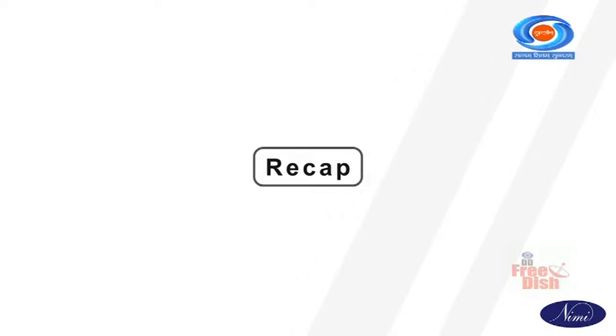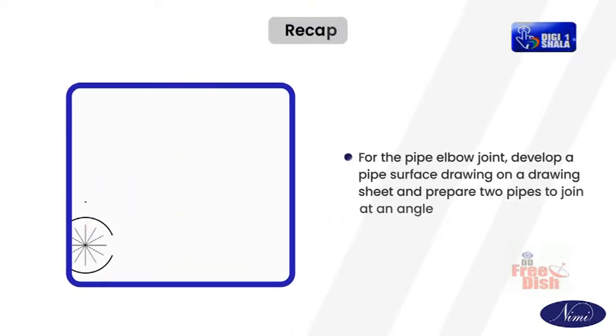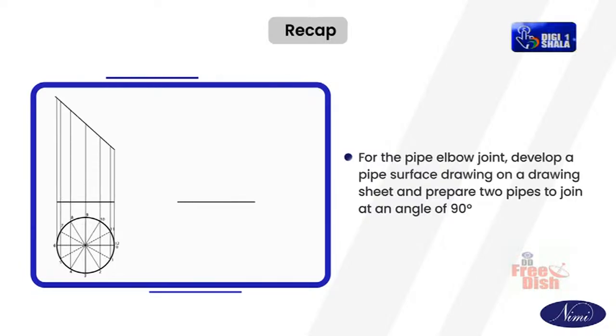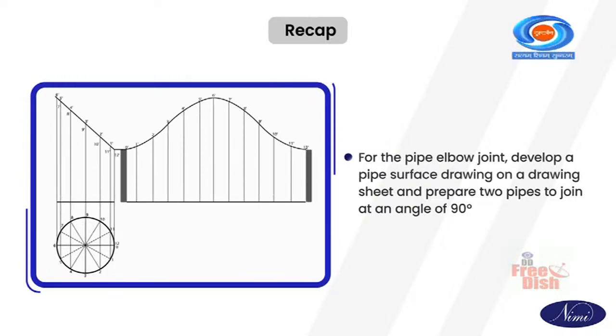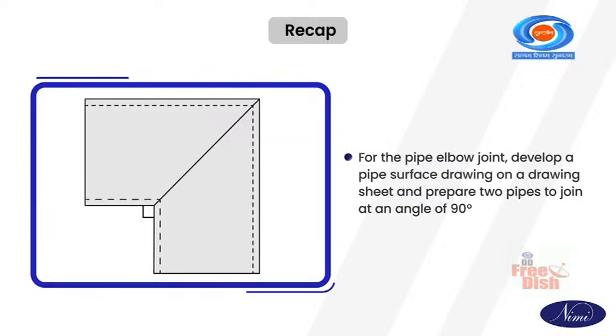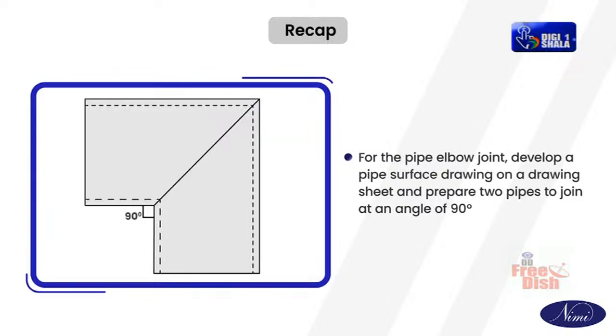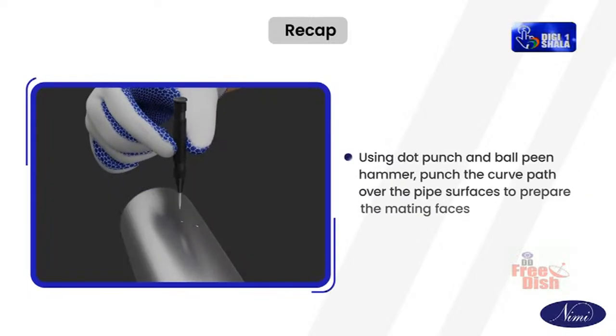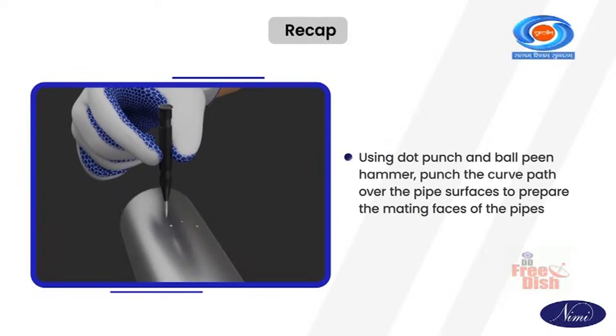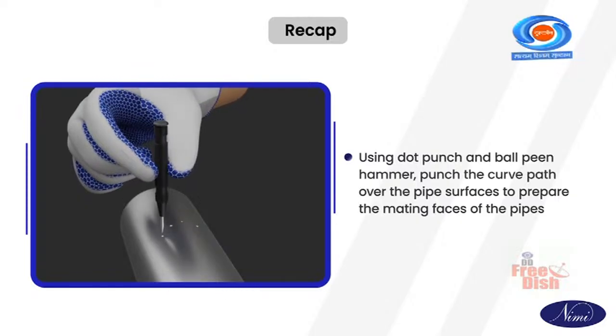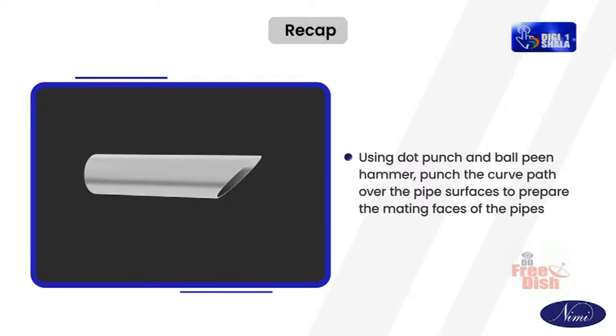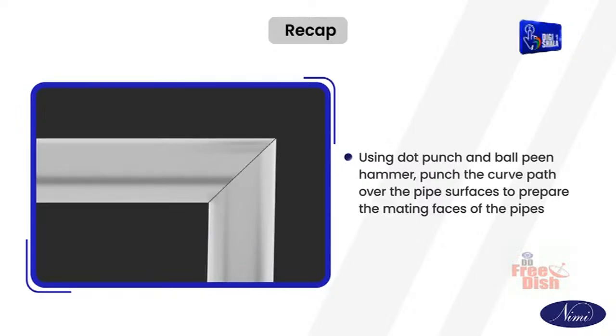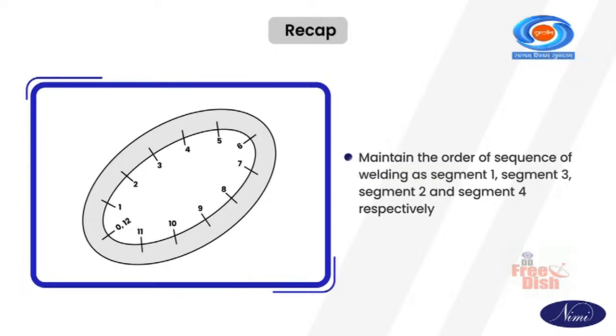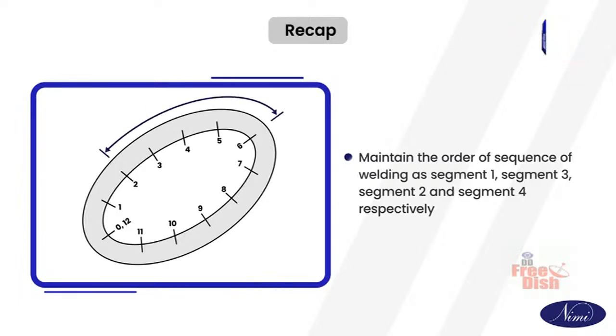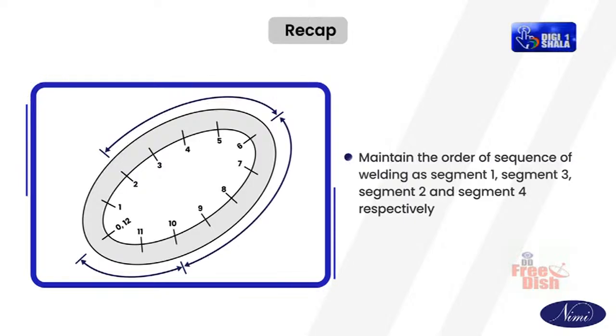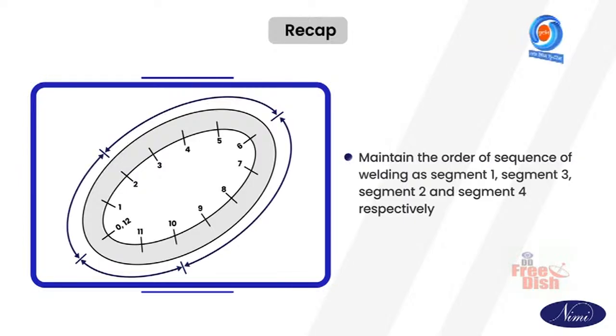Let's recap the key points discussed. For the pipe elbow joint, develop a pipe surface drawing on a drawing sheet and prepare 2 pipes to join at an angle of 90 degree. Using dot punch and ball peen hammer, punch the curve path over the pipe surfaces to prepare the mating faces of the pipes. Maintain the order of sequence of welding as segment 1, segment 3, segment 2 and segment 4 respectively.